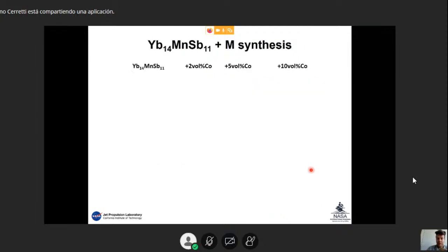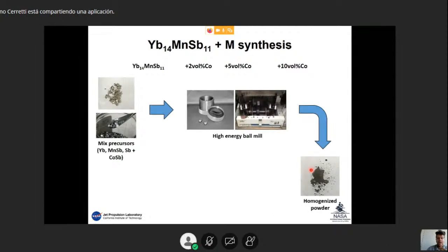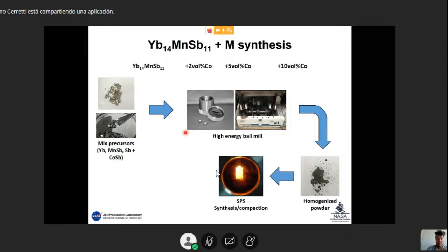I prepared different compositions. I started with 2, 5 and 10 volume% cobalt. For the synthesis of the materials, as I said, we started from raw materials. We do a high energy ball milling, which is basically a kind of shaker. We have this vial, we put the elements inside, we add these balls, and this is like a high-speed shaker. What we obtain are homogeneous powders, so the elements are homogeneously dispersed inside the powders. We then use sintering techniques to obtain high density pellets that are then used for the characterization of the properties.